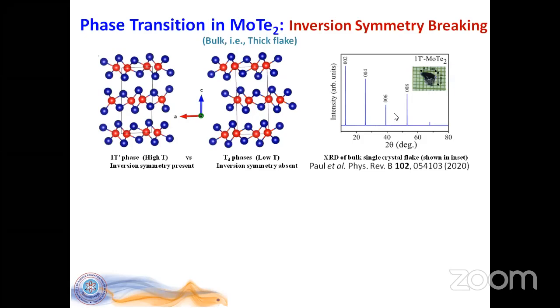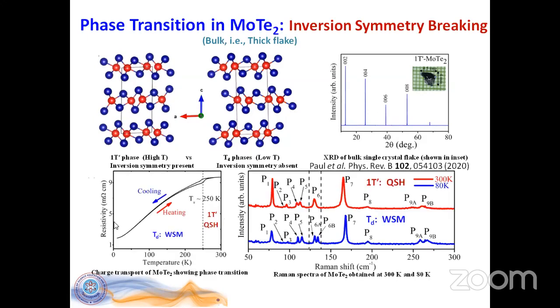And this is the X-ray diffraction data of the single crystal grown by Ravi's group. And now, if we look at the typical transport, the 4-probe transport property, the resistivity versus temperature of this system that is undergoing the structural phase transition, we see that in the high temperature phase, which is also known to show the quantum spin Hall phase, it undergoes this change in the resistivity, and then this comes out to be the Weyl semi-metallic phase in the Td structure. And then upon the cooling and the heating, we see that there is a clear hysteresis right about 250 or 240 K in the system.